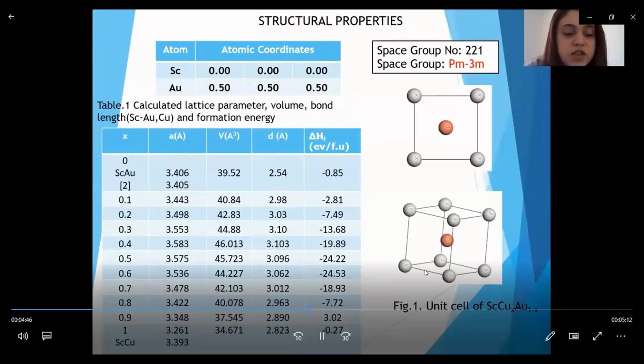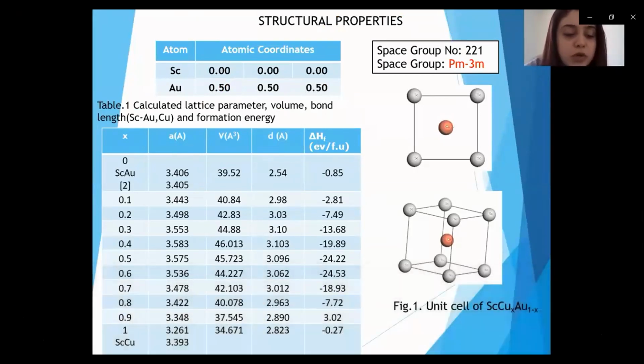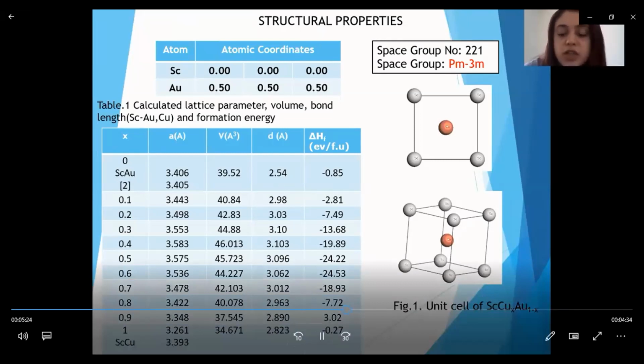In the present work, the structural parameters of copper-doped scandium gold B2 alloys are obtained through structural optimization, in which the different values of doping ratio X of the scandium copper gold alloys are set to be in range from 0 to 1 by using the VCA method in the B2 structure. Figure 1 shows us the unit cell of scandium copper gold. The atomic coordinates of the atoms placed in the unit cell are shown in the table above. And Table 1 shows us the calculated lattice parameter, volume, bond length, and formation energy.